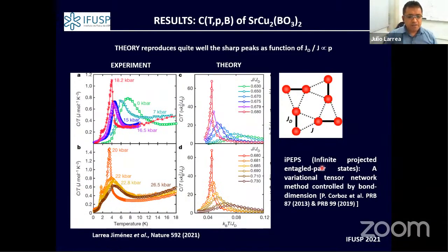Based on the infinite projected entangled pair state models, that basically calculate the eigenstate at finite temperature, what we can see is that theory managed to reproduce the sharp peak by simply considering an increase of the density of population of the triplet state.